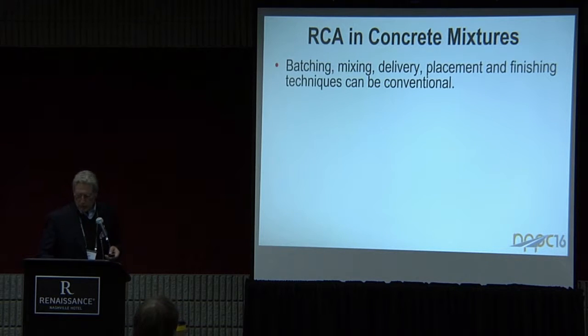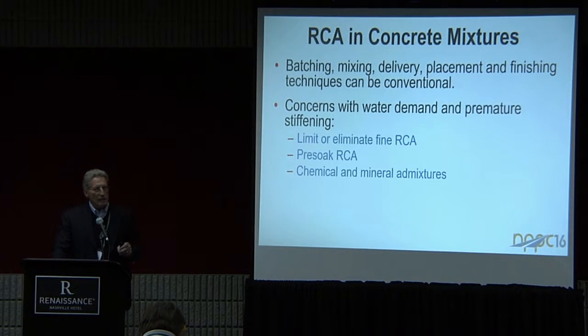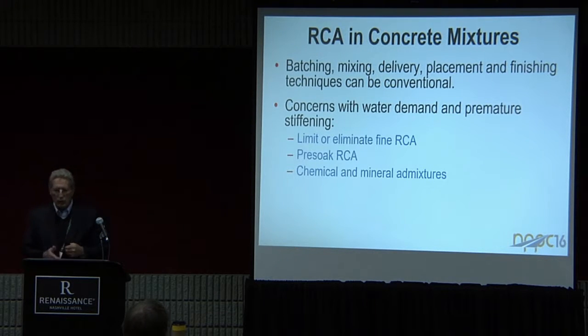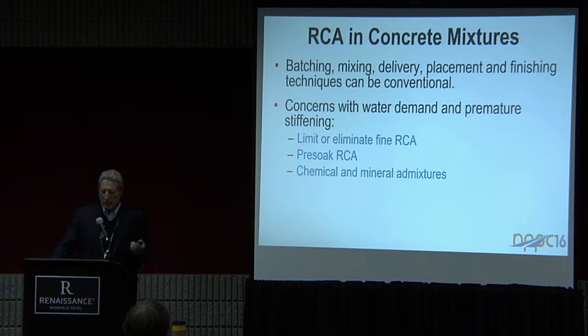When you're doing it into concrete mixtures, it's pretty much conventional batching, mixing, delivery, placing, and finishing techniques. We may need to adjust the mix design a little bit. Our proportions may be a little bit different because, given the more angular, rough textured nature of the particles, it's going to be a little bit harsher mix to work with. So to address that, we can eliminate or limit the amount of fines that are used. Again, holding it down to 20-25% fines if they're used at all seems to work pretty well.